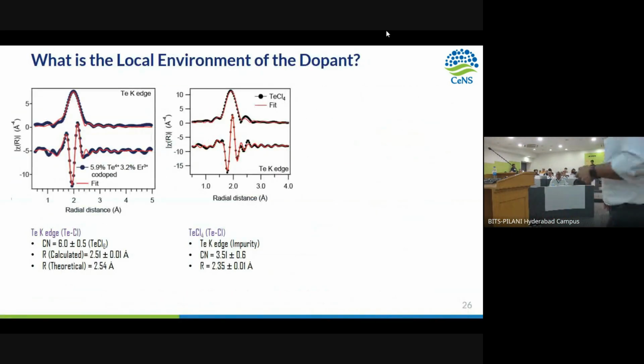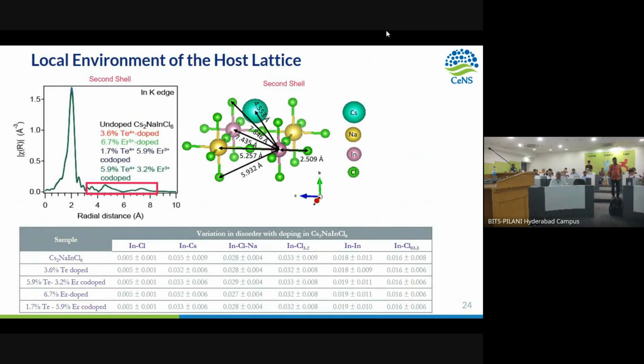Very nice talk, Pralay. My question is about your slide number 24. There you have mentioned that the distance between the central metal atom and the third shell neighbor is 7.435 angstrom. So it's very far away. How much certainty do you have in figuring out this shell? Typically the EXAFS oscillation, the scattering, dies by 6 or 7 angstrom.